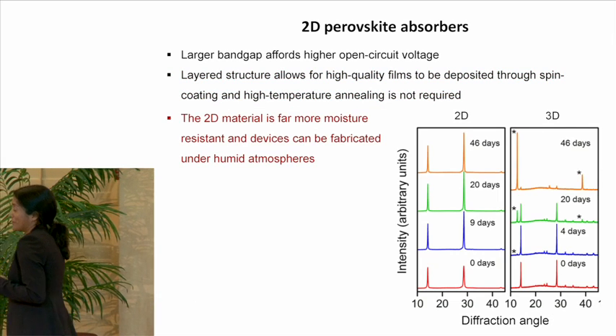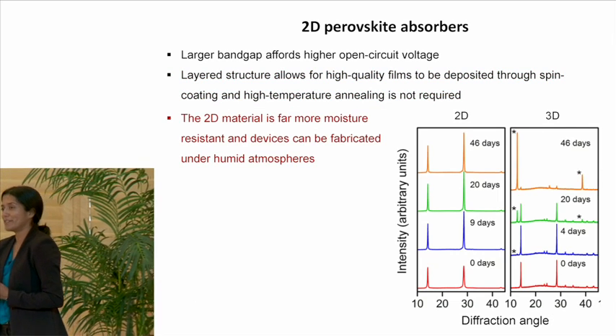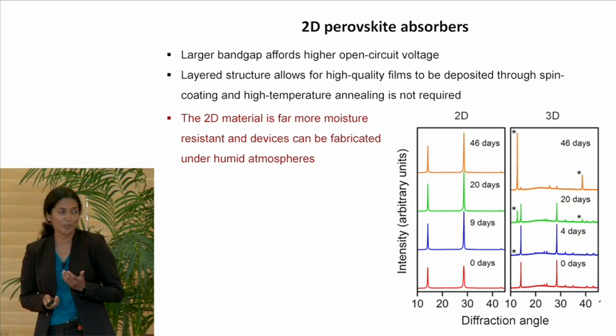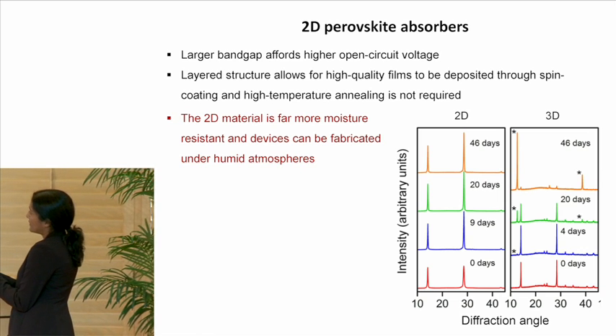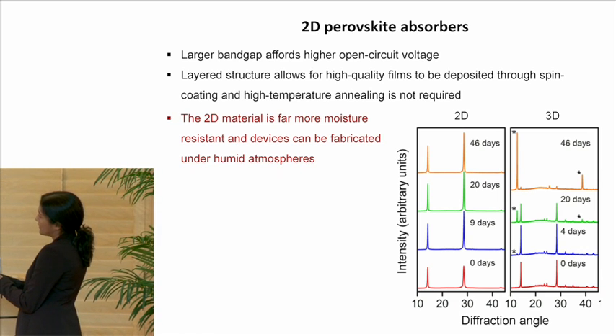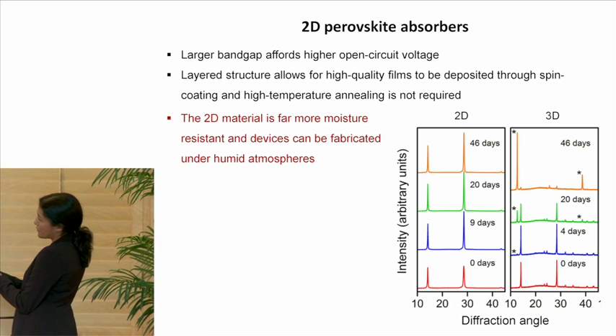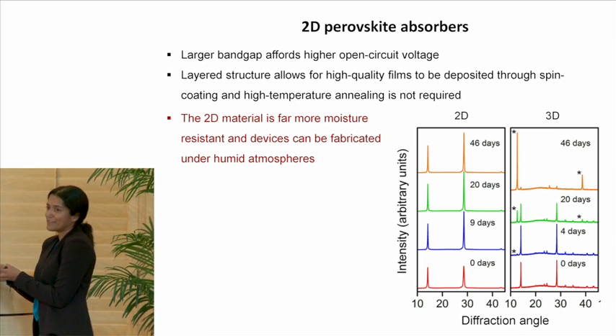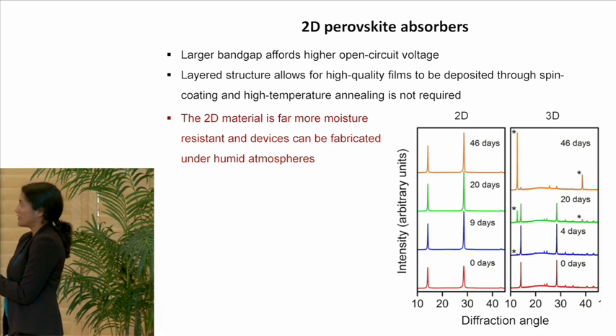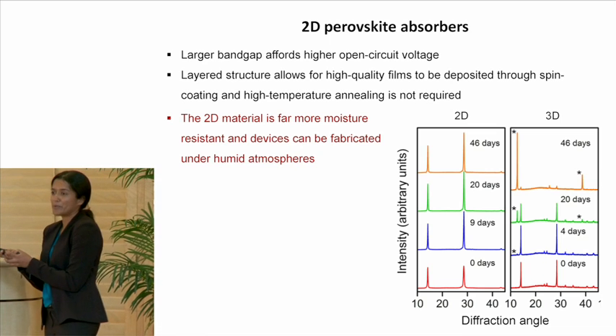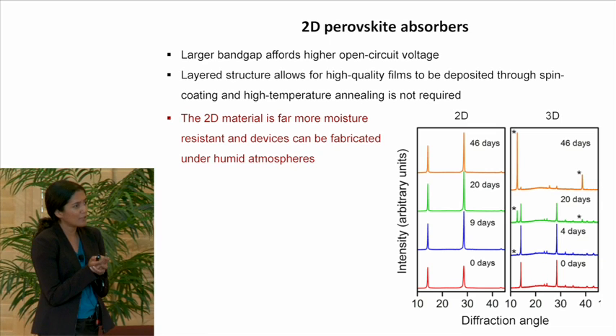And by far, I think the most important point here is that the 2D material is a lot more stable to moisture. So with the 3D material, here I show you powder XRD patterns, and over time, we see when this is exposed to about 50% humidity, we see the growth of new peaks, which completely dominate the spectrum after about 40 days. This is lead iodide, whereas in the 2D material, this material is pristine, untouched by lead iodide over 40 days.